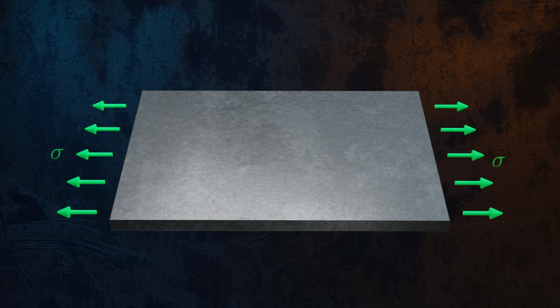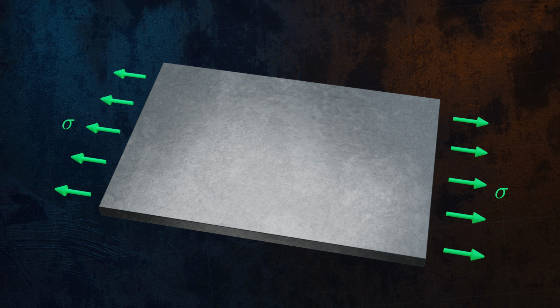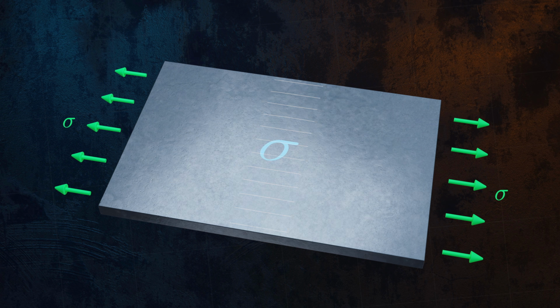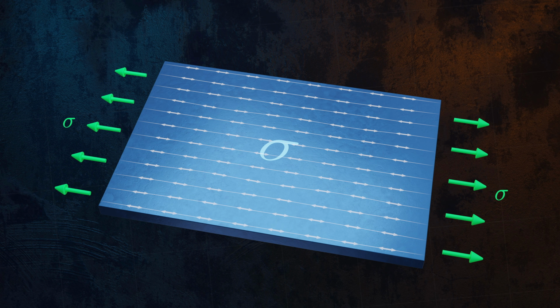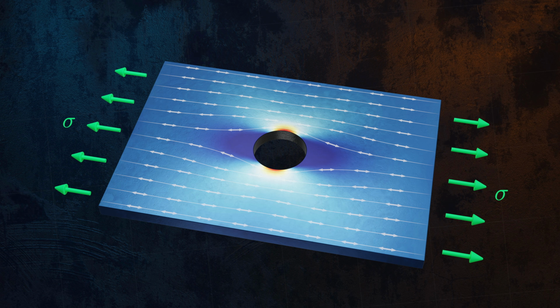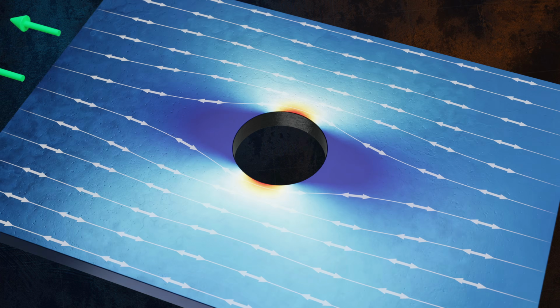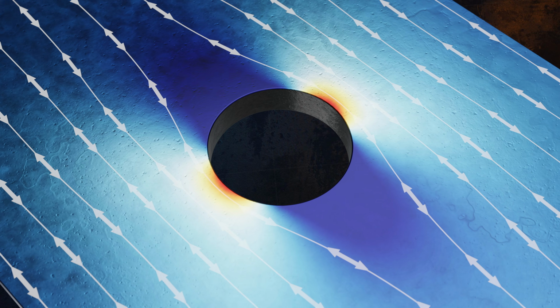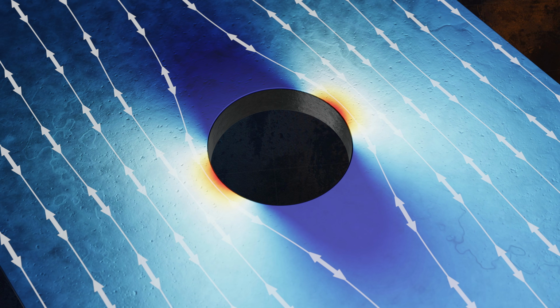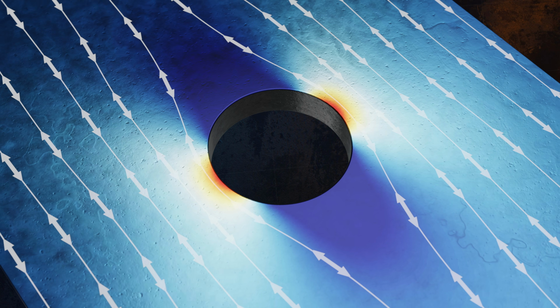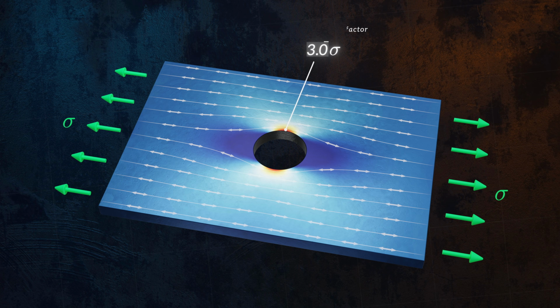If you take a plate and pull on it at both ends, a uniform tensile stress will develop within the material in response to the applied load. This stress is spread evenly across the material. Drill a hole in the plate, and this uniform stress field is suddenly disrupted. Stress flows through a material a bit like a fluid, and the hole forces that flow to detour around it. The flow lines crowd together at the edge of the hole, which increases the force per unit area in that region. The maximum stress in the plate at the edge of the hole reaches 3 times the applied stress. The hole creates a stress concentration factor of 3.